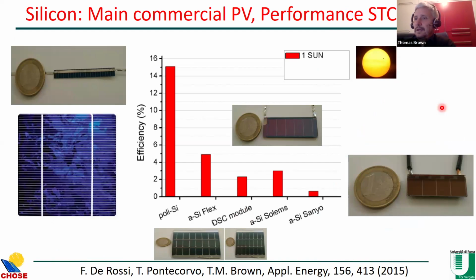And here we are testing commercial devices. So polycrystalline silicon device, which is this one. And the efficiency under standard test condition was 15%. So at that time, it was an average efficiency for polycrystalline solar cells. Now they've gone up to 18, 20. Then we tested amorphous silicon.